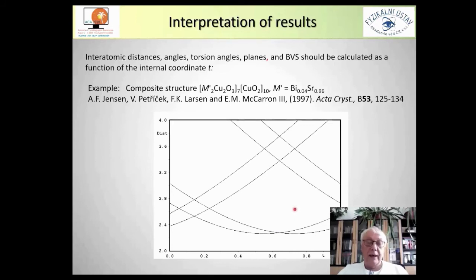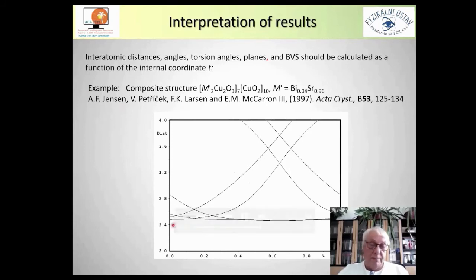If we go to the composite structure with modulation, the situation looks very different. The modulation between these 2 subsystems makes these distances almost constant. For 2 oxygen strontium distances, almost constant. This means the driving force of our modulation is the distance between strontium and oxygen.